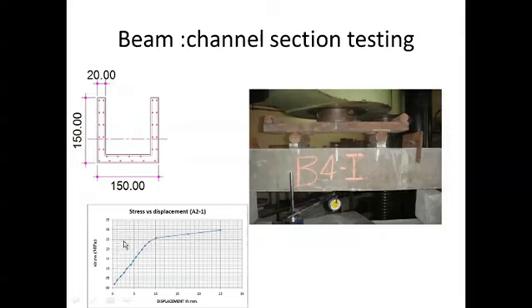This is the measured value of flexural stress, and we could also plot load versus deflection of this beam. We could see that up to a certain limit there is elastic behavior, and beyond that it has toughness, so we can say it's a non-linear zone for this beam, but still we are reaching an ultimate flexural tensile strength of 29 Newton per mm square.